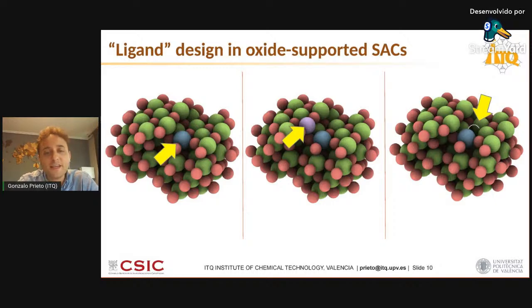The third possibility is to design our oxide material, our support, as to its propensity to create vacant sites in the direct coordination environment of our metal, typically oxygen vacancies, for instance. That's something that we can also consider, and we can engineer to some extent in our catalysts. And those can play an important role in single atom catalysis, where very seldom, if at all possible, would the whole catalytic cycle be run by the single metal center without participation of some of the centers, either Lewis centers or oxygen vacancies and so on, in the direct neighborhood of it.